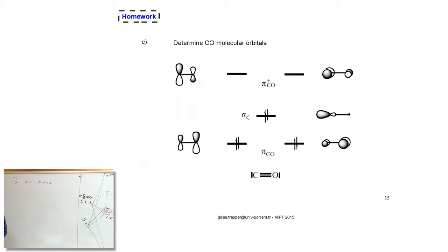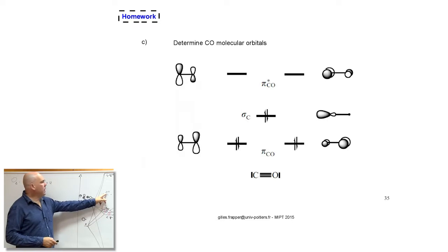So you may ask why it should increase. If you take into consideration that carbon may give 4 valence electrons, with an oxidation number of 4, you will fill these levels with 2 more electrons.